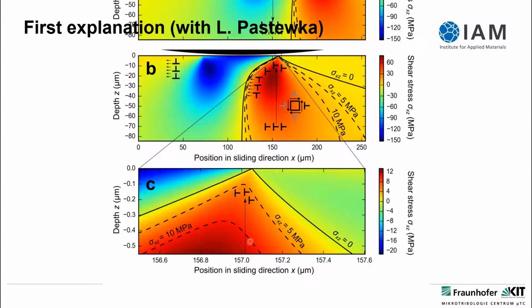So basically what we are assuming is the dislocations are sucked up towards the surface or pushed towards the surface, but not completely to the surface. So they will stop moving here, and that's where they will self-organize into this dislocation trace line. If we look at the depth under the surface where this is happening, it's roughly 150 nanometers, which is also where we experimentally observed the dislocation trace line.